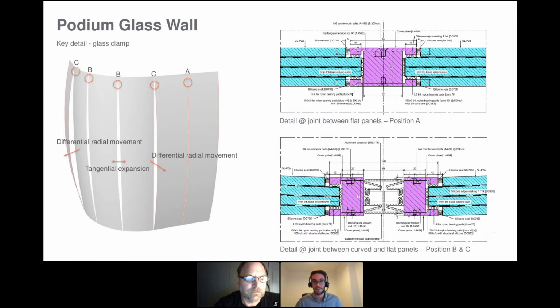So what we thought was to introduce a movement joint and therefore decouple the two panels, introducing two separate rods, which can move independently from each other out of plane and expanding with the movement joint, coping with the differential movement. What we had to introduce as well was something to prevent the two panels from moving together when there is some pressure applied on the glass corner. And we did that through some bearing, some steel aluminium extrusion, which allowed the two panels to bear together, so to avoid any movement inwards.